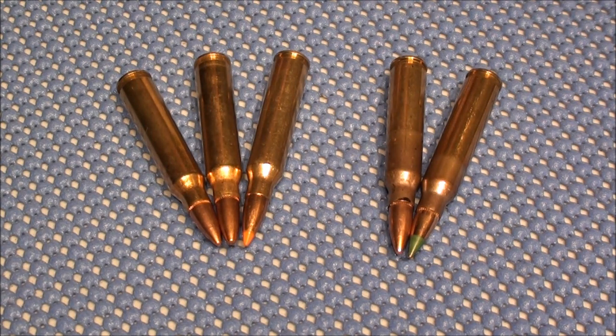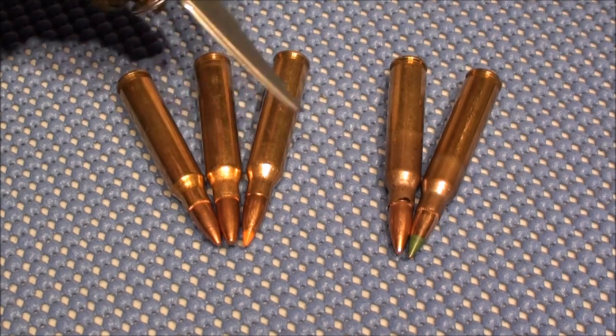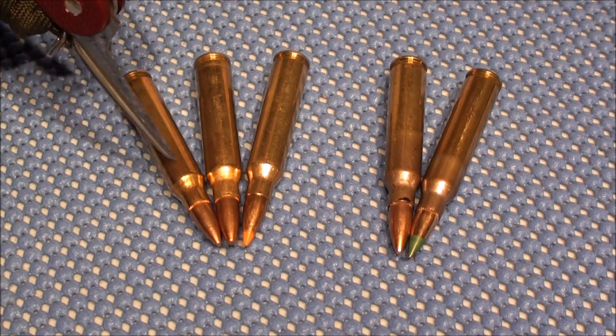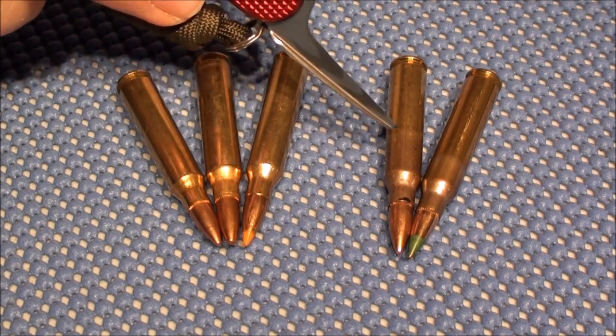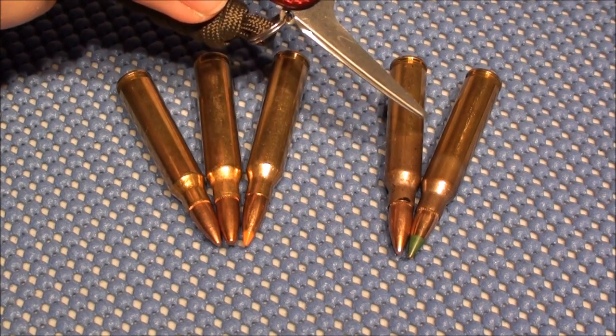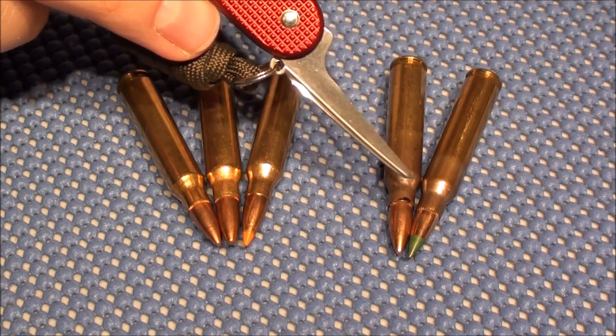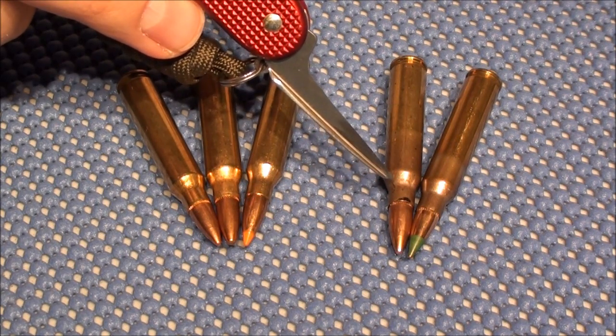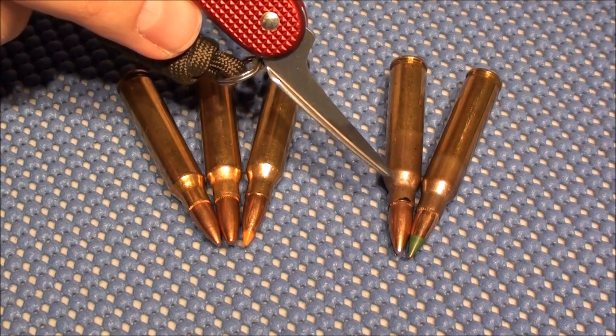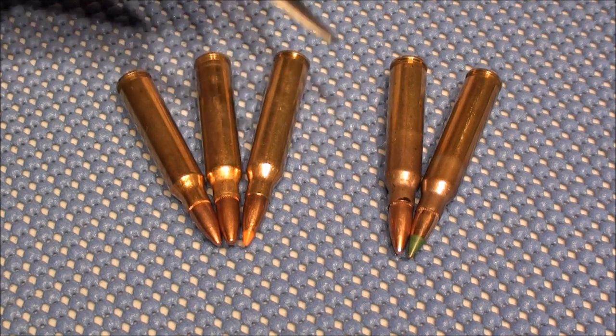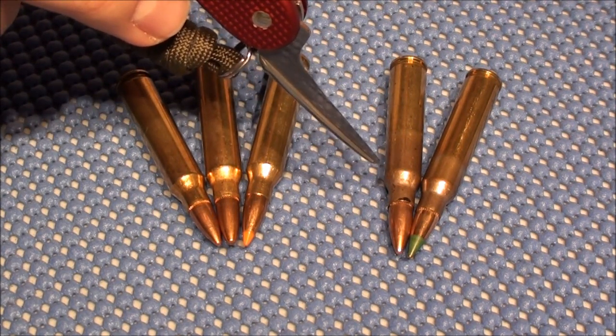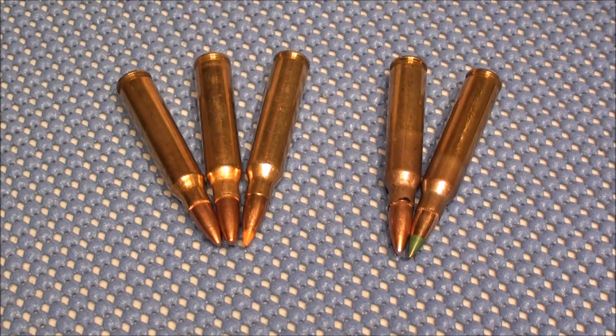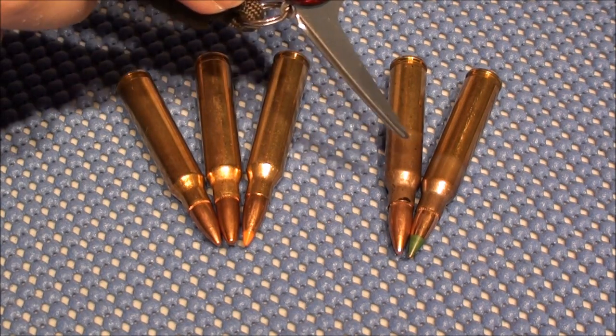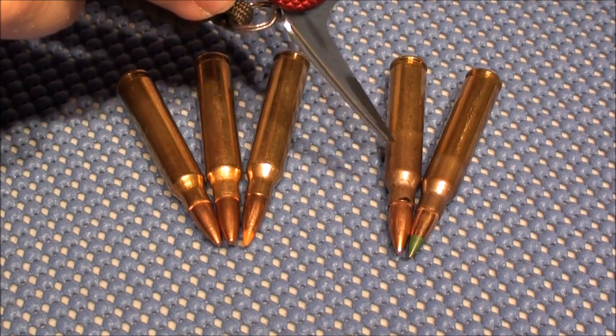Another thing that you can notice that is different here between the 5.56 and at least the commercial .223 rounds that we have here in front of you is this discoloration of the brass. What this is called is annealing, and it's actually been heat treated. Now the difference between brass and steel is that when you heat treat steel, you make it harder and more brittle, whereas if you heat treat brass, you actually make it softer.